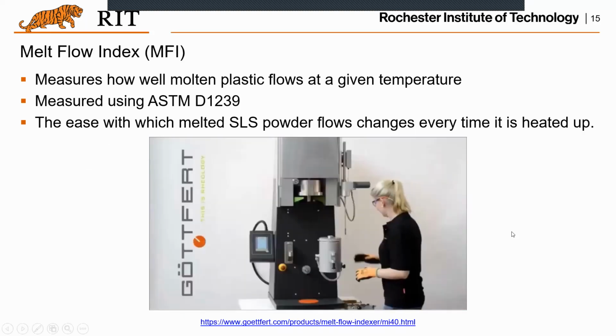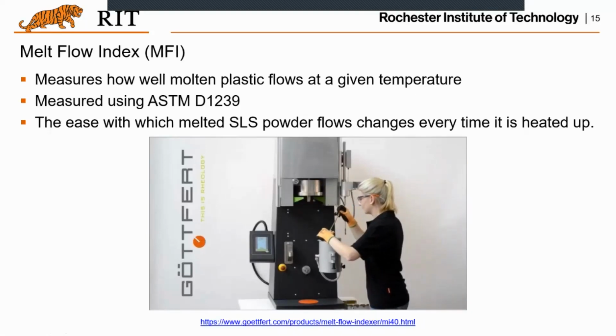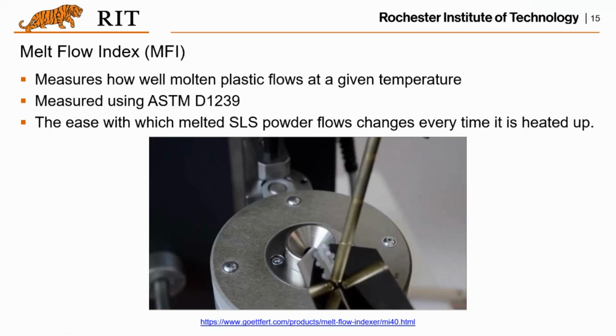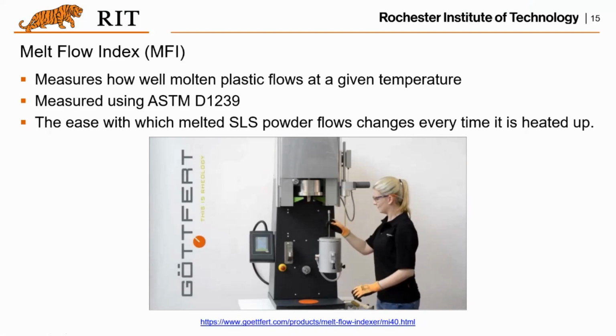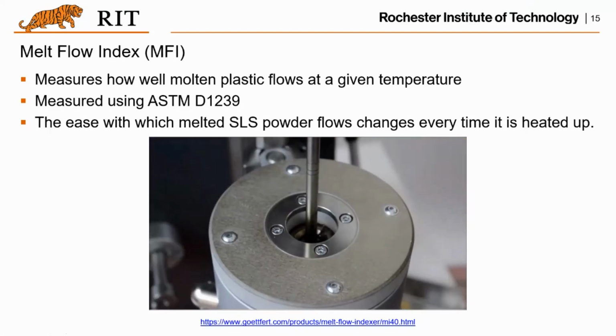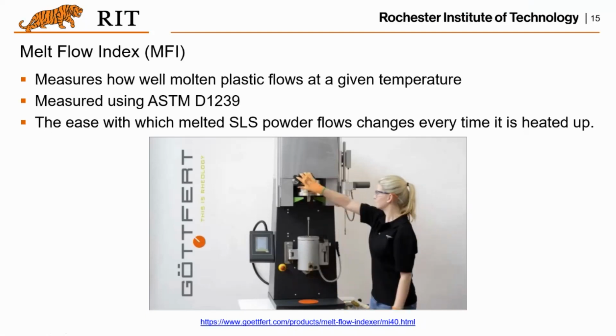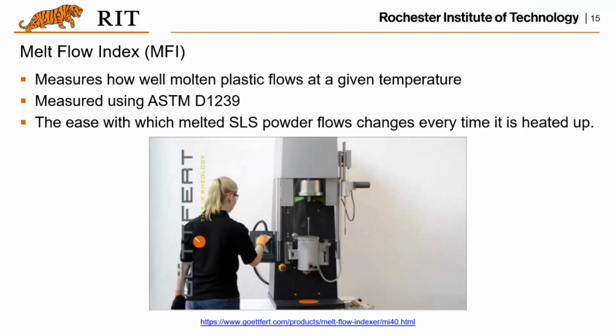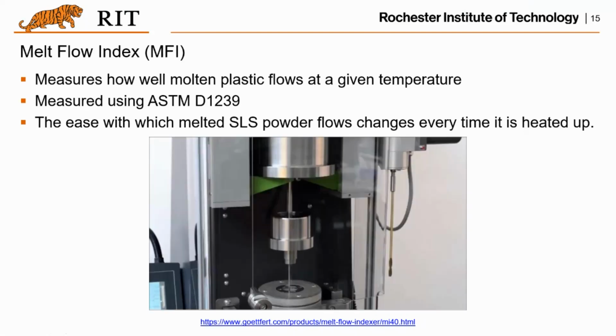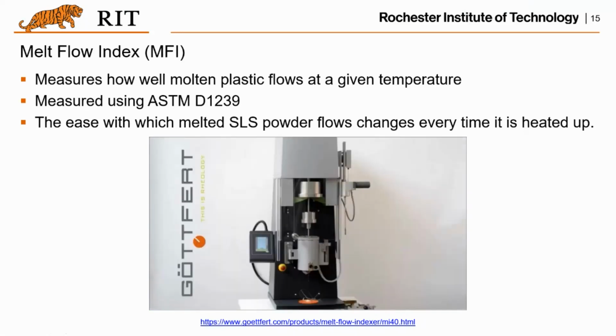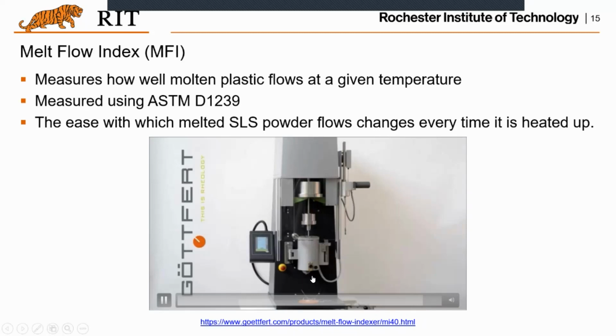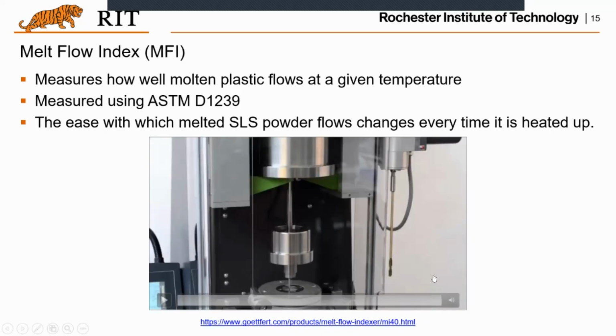So there is a way to determine the melt flow velocity if we conduct such a test. Basically, this is the melt flow index testing, and that is measured using the ASTM D1239. As you can see here, we have the pellet of the plastic, and it will be heated up in this device, and then it will measure how the molten plastic flows at a certain set temperature. See, that's how it works. As you can see here, at the bottom, it flows through a small hole, and all the parameters will be recorded accordingly.